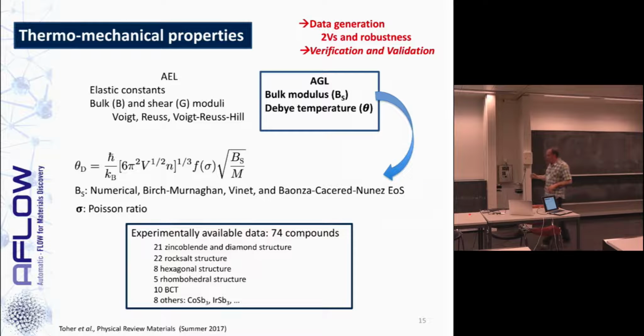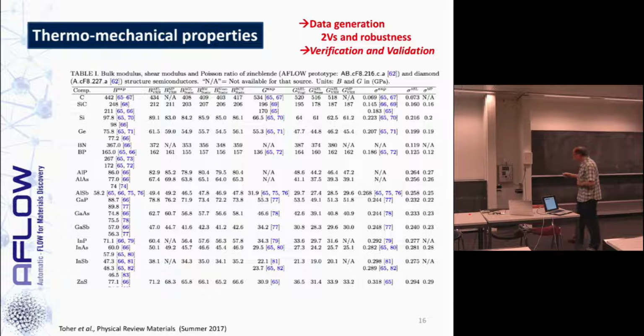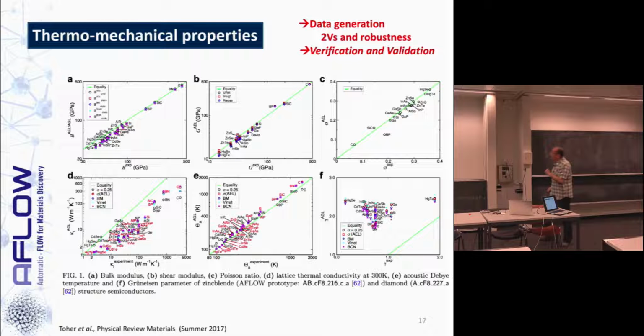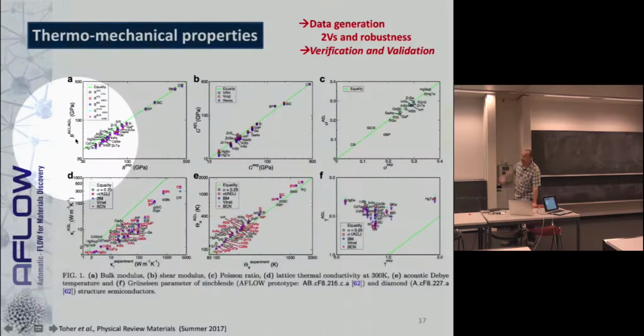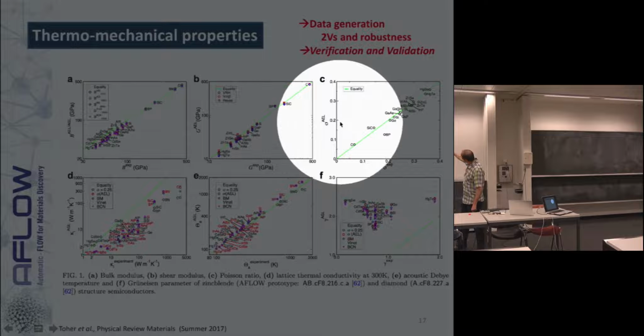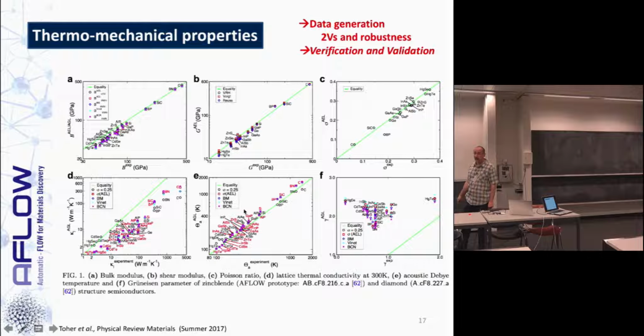So we processed those, and then we selected 74 compounds that were available in the literature with very accurate data and of different structural types, in order to validate our predictions and tell which one was good and which one was not as good. We computed many of these tables. You can imagine we have a lot of data. The results, for instance, for the zinc blende or diamond structure can be seen very clearly here. On the horizontal axis, we have the experimental data. On the vertical axis, the data computed with different methodologies. You can see that, for instance, the bulk modulus, the shear modulus, the Poisson ratio, and the Debye temperature are coming out very well, mostly regardless of what kind of fitting you do, what kind of equation of state you're using, or whether you're using the elastic library or the Gibbs library.